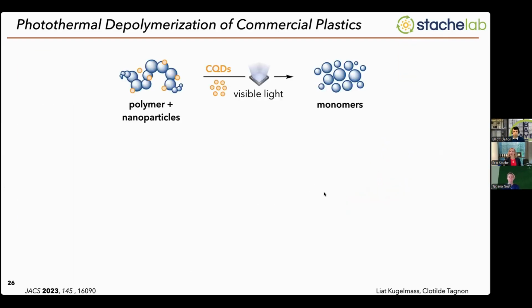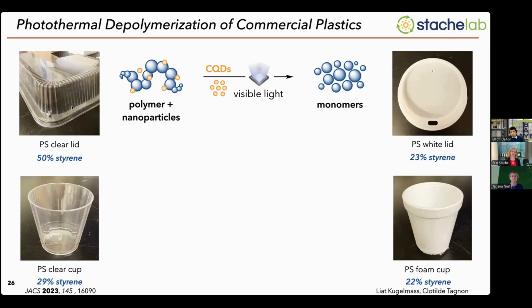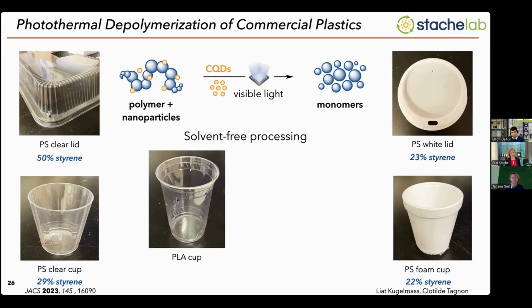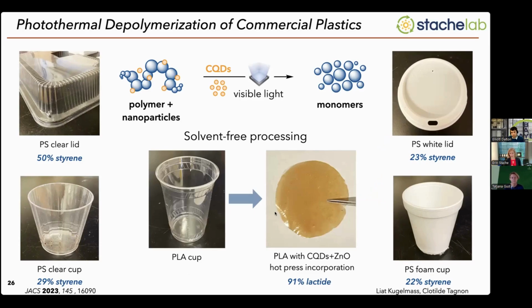Undeterred, we tried this in a number of different commercial samples. So again, the clear lid, clear cup, Styrofoam cup, and then the coffee cup lid. And in all cases, we could mix the carbon quantum dots with the polymer in solution, remove the solution, irradiate, and generate styrene monomer. Very excitingly, we're able to do this in a solvent-free processing method. So we could take solid carbon quantum dots with post-consumer waste, so PLA, mix them together through thermoforming, so just hot pressing them together into a film, and then we could irradiate this without any real loss of efficiency. We can actually lower the catalyst loading as well to get L-lactide monomer back.